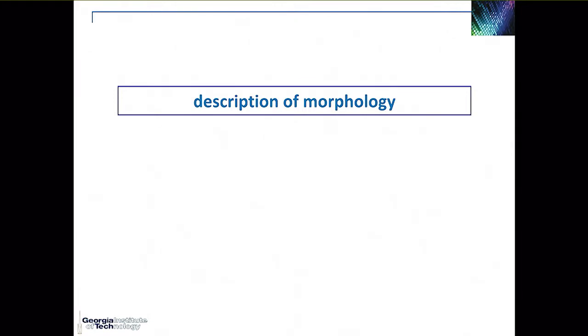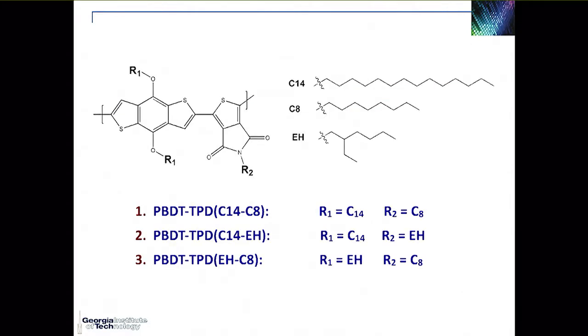In that case, then we went to descriptions, attempts to describe the morphology at the molecular dynamics level. And we considered the 3 types of polymers that Pierre Beaujuge synthesized. And the point I would like to emphasize here is the following. In the case of the first polymer, I have only normal side chains, alkyl side chains. In the case of the second polymer, I have a branch side chain on the electron poor moiety, but that's only 1 branch side chain per polymer repeat unit.